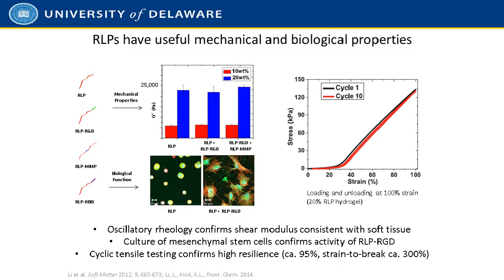These materials, as I mentioned earlier, have good and tunable mechanical properties. As shown here in the bar graph, you can see just by changing the concentration of the materials, we can get shear storage moduli that are perfectly consistent with what we expect in soft tissues, and that the RLPs are not toxic to cells. You can see there's good cell viability, and in fact really high cell viability in these materials, but only when they carry the RGD domain, which is a canonical cell binding domain, do cells spread on these materials. And I show here tensile loading and unloading of over 10 cycles of a resilin-based material, illustrating the great resilience and the lack of hysteresis in the loading and unloading of these materials.